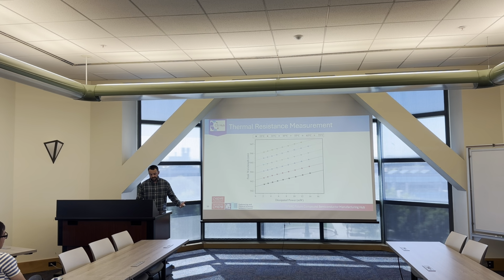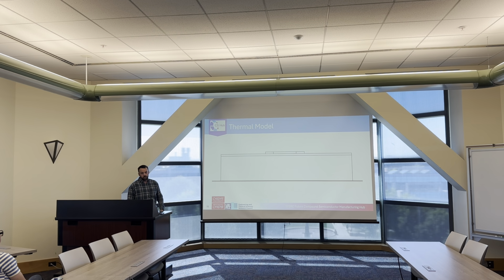So, example of the data sets: we've got peak wavelength versus dissipated power as a function of temperature. Then we can get the wavelength shift with dissipated power from the slope. Extrapolate to zero dissipated power and see that as a function of temperature to get the wavelength shift with temperature. Okay, so we want to do some fits to that data as well to extract conductivities. So this is the thermal model for that.